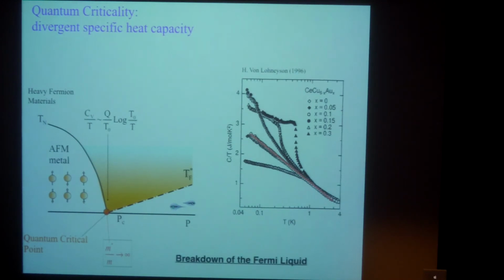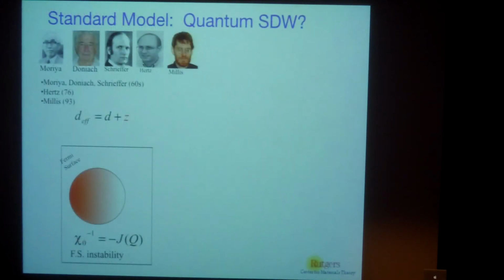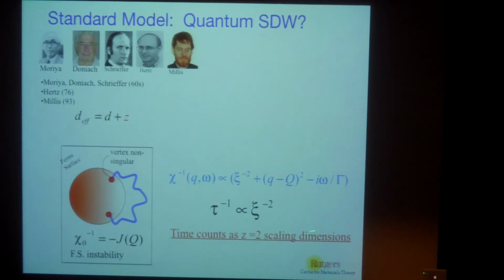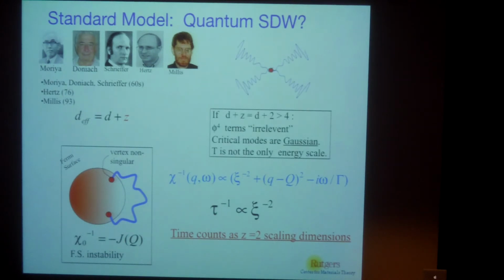And although a lot of effort has been expended on this problem, and some of the systems can be understood in terms of a kind of spin density wave transition, there are many bad actors, such as this system, which don't fit into that behavior. And we're looking for a new description of this quantum critical point. This is the standard model, the quantum spin density wave picture, often known as the Millis-Hertz approach. And the basic idea is that quantum criticality is driven by soft magnetic fluctuations, which induce long-range interactions that break the Fermi liquid down. The problem with this model is that actually time counts as 2 dimensions in the scaling theory, and this means that when you're in 3 spatial dimensions, these soft modes don't interact strongly at long distances. You get what is a Gaussian fixed point. Whereas to understand the unusual physics of these systems, you need to have something that would involve interacting modes, which for such a model would require a dimensionality less than 2.